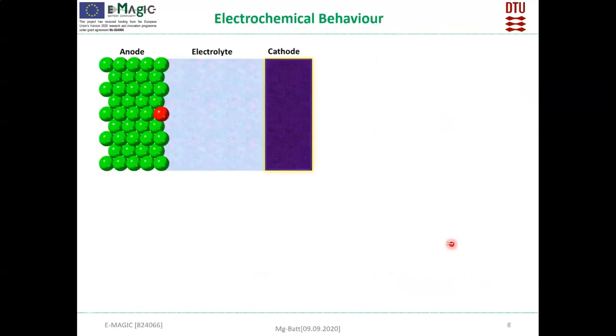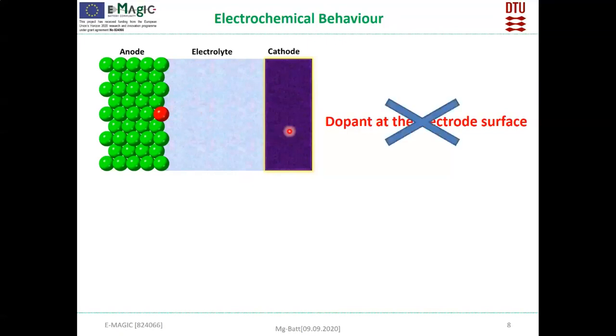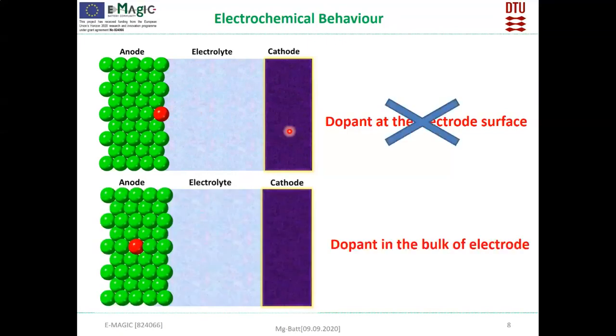And the final thing is we want to know the electrochemical behavior of this dopant. So this we evaluated based on where the dopant goes. We want to know whether the dopant will go to the surface. If the dopant goes to the surface, then there's a chance of the dopant reacting with the electrolyte, which may affect the electrochemical performance of the battery. So that's why we don't want the dopant to be at the surface, but we want it to be in the bulk.